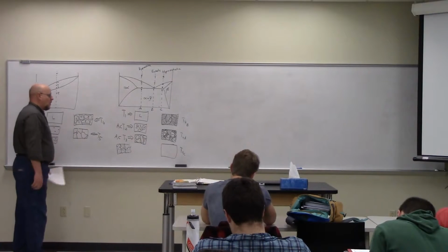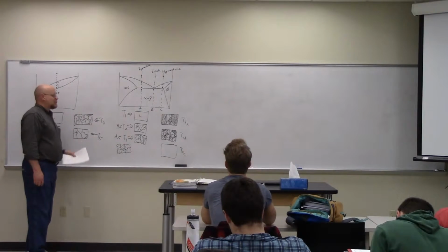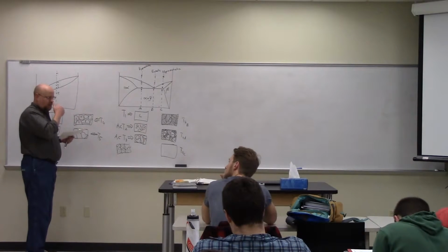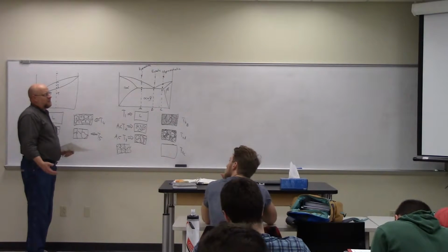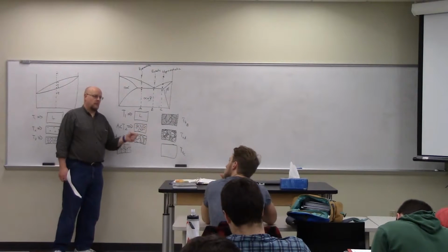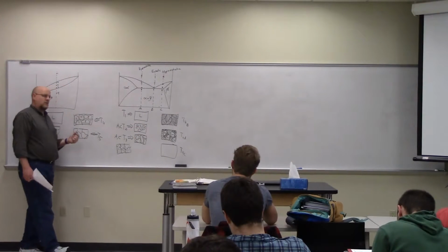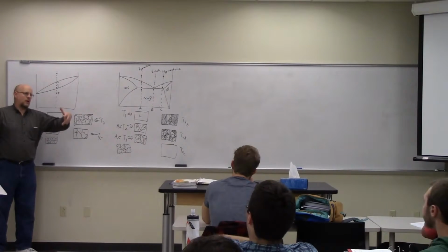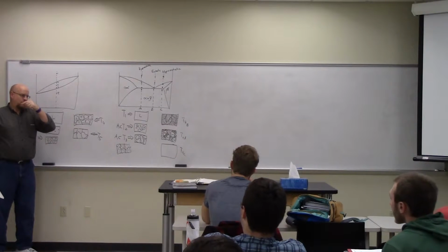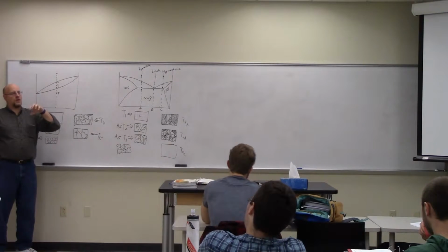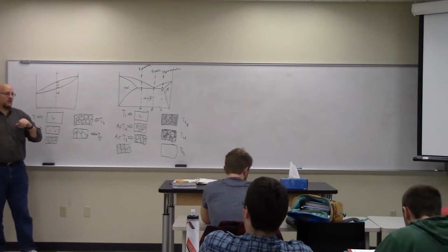Is it possible to get a structure where you have crystals of just alpha and just beta? I suppose if you went, no, because they're gonna, yeah, no. I mean, if you did, they would be very small crystals. Little small grains of alpha and beta. And generally speaking, you're gonna want to plate one on the outside of the other. Because, as we'll talk about next time, there's a lower energy and a greater likelihood of nucleating a new grain on the surface of an existing solid.